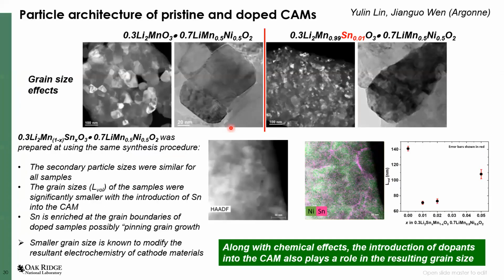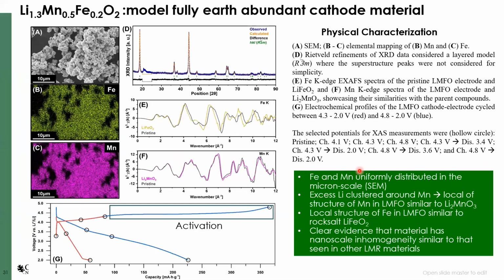So to further confirm that, we did transmission electron microscopy, and we can clearly show again here that the tin is present in these regions which are near grain boundaries, which we believe comes because these local domains are trying to purify themselves of the dopants that we are putting in, and it's pushing them to the grain boundaries. It turns out that doing this helps to reduce the area-specific impedance of this material. So we are continuing to follow up on this, and hopefully we'll have a better solution for trying to manage or mitigate the high area-specific impedance that is seen for these materials at low states of charge.